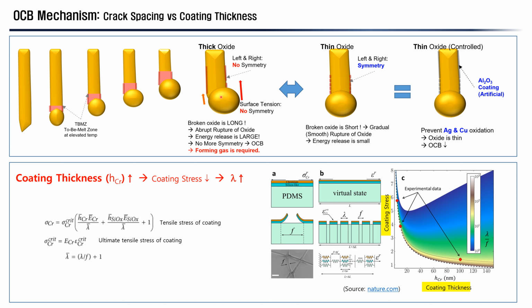This whole thing occurs over a very short period of time, so it is very difficult to provide a proof of this phenomenon. But anyway, when the thickness of oxide is very thin, there is little interference with the molten ball surface tension, so there is stability. On the other hand, when we apply aluminum oxide coating on the surface of the bond wire in an artificial way, this is nothing but a passivation. This passivation is not going to allow any additional metal oxidation of the bond wire itself, so that we can control the metal oxidation of the bond wire.